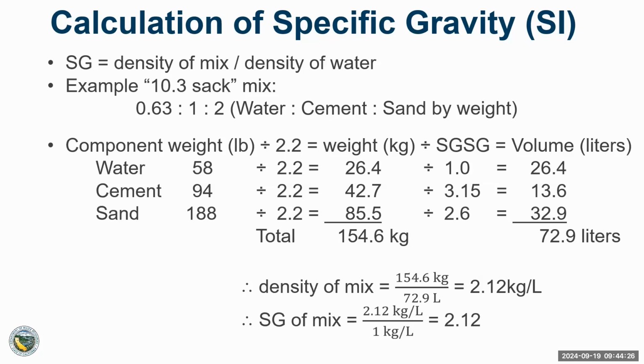Now we then take the weight and we divide it by the specific gravity, the solid grain specific gravity. And the beauty of the metric system is that water is 1. Cement is 3.15. Sand is variable, but we take 2.6. So you divide the weight by the gravity there, and you get the volume of these materials. So if you total the volume, you now have the weight of that mix, you now have its volume. You divide the weight by the volume, that gives you the specific gravity, the density. So now you're in the field and your target is a 2.12, and you routinely test that mix and you get 2.10 or 2.14, you know that your mix that you're injecting is exactly what you want it to be.